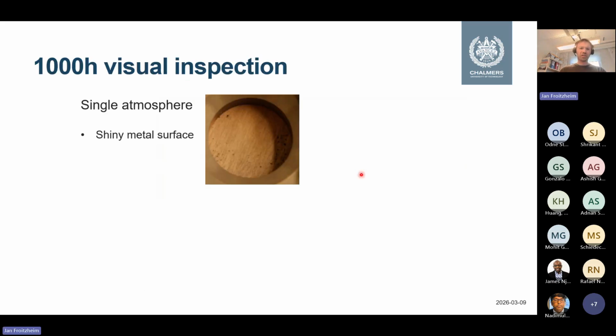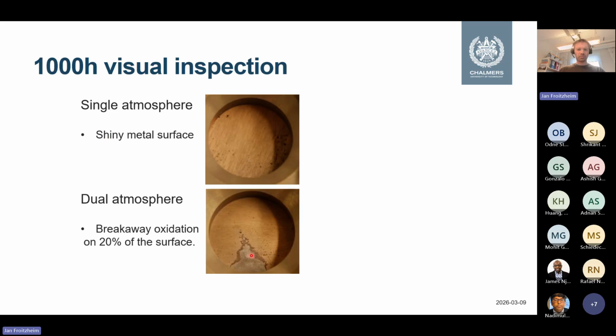So this is after 1,000 hours, visual inspection, 600 degrees C, so relatively low temperature. You see we have a relatively shiny metal surface, so everything is fine in single atmosphere, air on both sides. However, if you do dual atmosphere, we get breakaway corrosion.